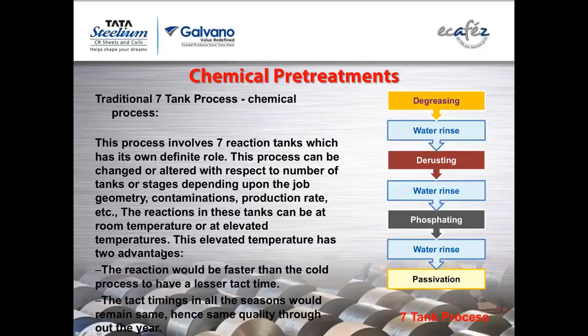These elevated temperatures have two advantages. Number one is the reaction would be faster than the colder process, so you will have lesser takt time. And second is that the takt time in all seasons would remain the same, hence the same quality throughout the year. So in a place like North Indian parts, the winter temperature could reach 2 or 5 degrees, where the tank bath temperature might be 10 degrees, and in summers it reaches 45, so the bath might be something like 35, 38. So you cannot expect the same reaction to happen in the same fixed time. So normally we prefer temperatures which are higher than the maximum temperature of that area.